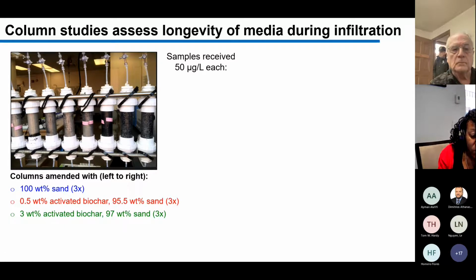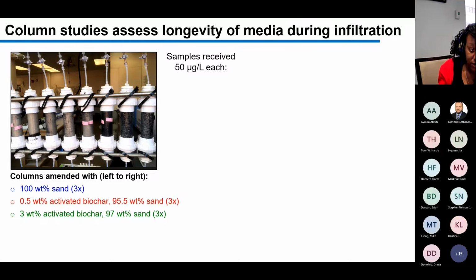Okay, so that was some initial characterization of the activated biochar material that we've been developing in my group. And what we wanted to do next was to start answering questions about how well this material could work to remove contaminants in stormwater. So here on the left, I'm showing lab scale columns that we built. And what's missing in this picture is this large tank at the bottom where we have tubing coming from that is injected up and then out the top of the column. And we have spiked this synthetic stormwater mixture that we created in the lab with different contaminants to mimic stormwater that would enter into a rain garden, for example.